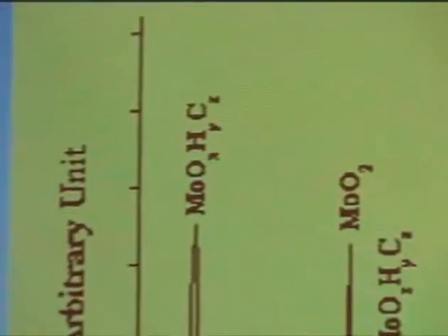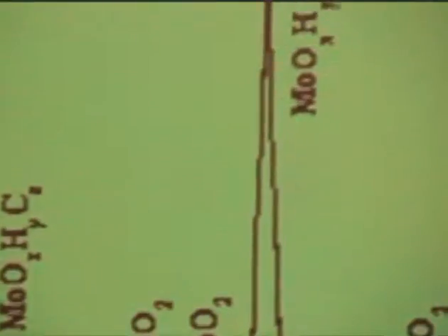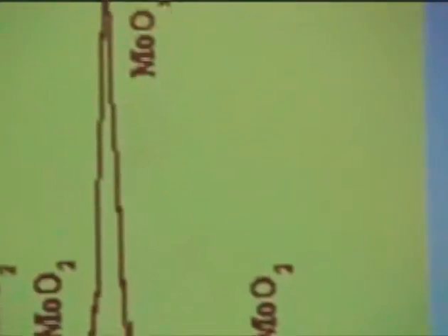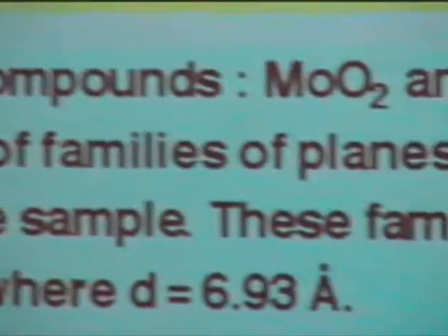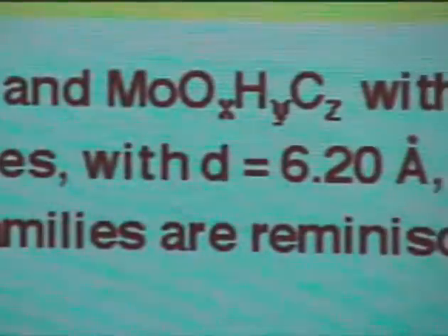So obviously we have MoO2. A little bit of MoO2 is formed during this carbon reduction. I will not enter now into the detail, but it's important to have this MoO2 at the beginning because MoO2 is able to dissociate hydrogen. And it is in fact a self-catalytic process.